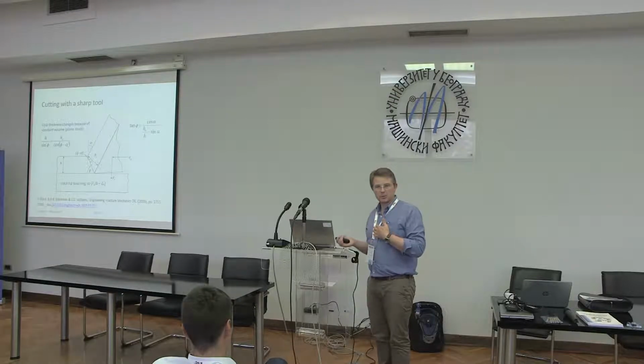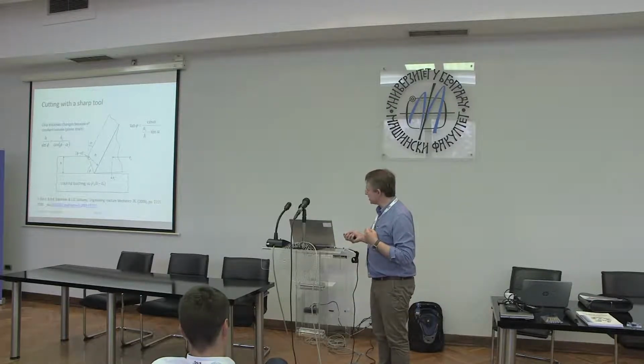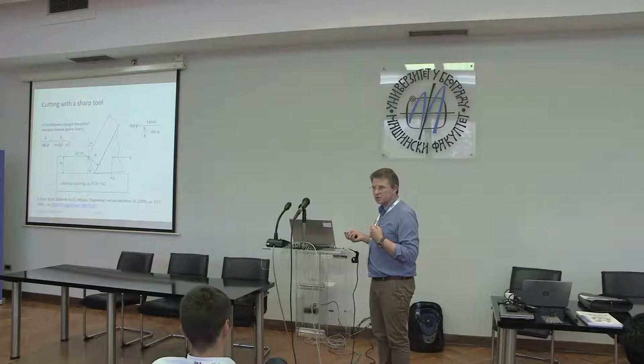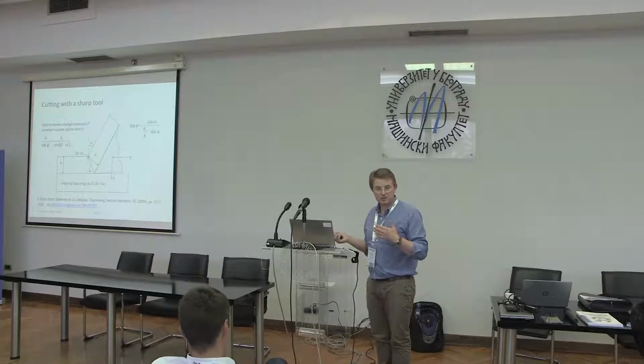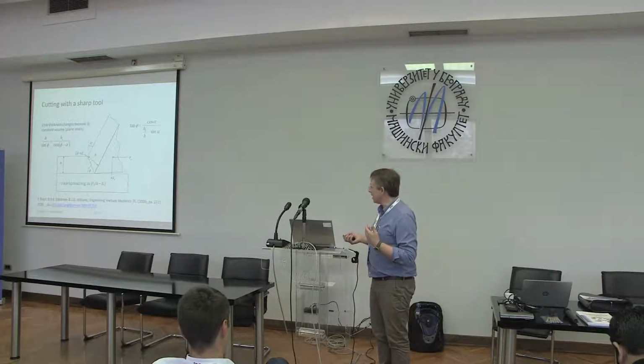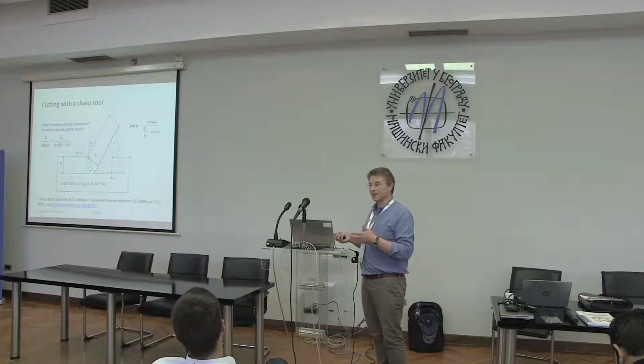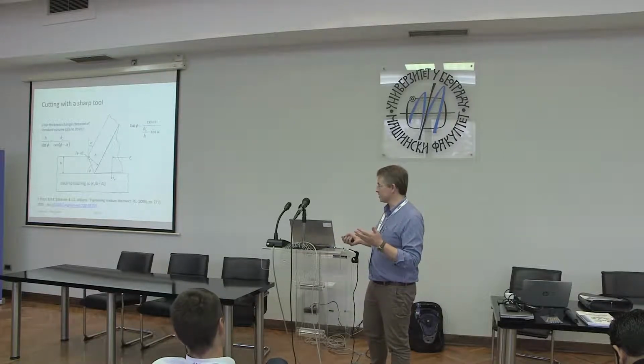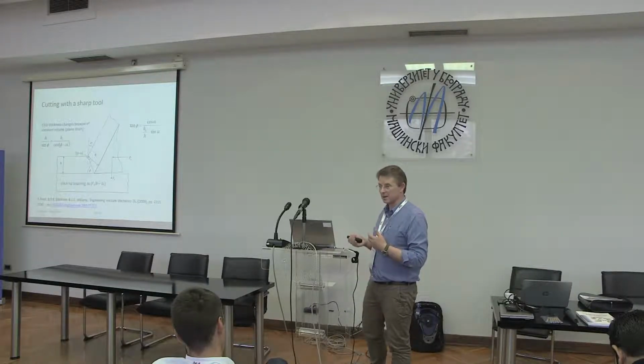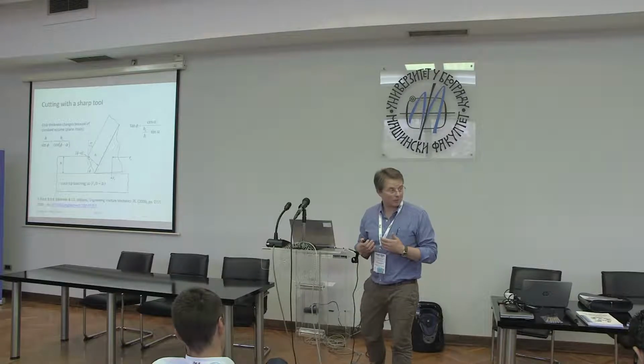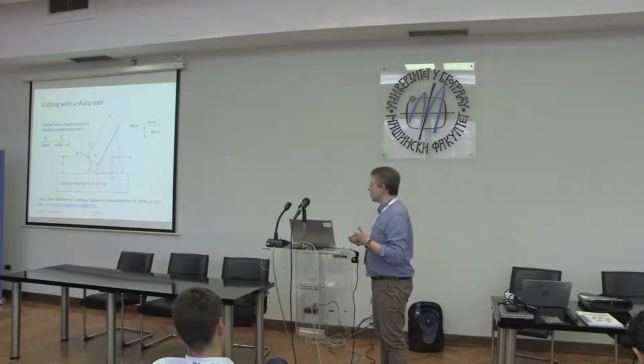And of course the basic idea really is that the plasticity in this point here is a function of the thickness. And in principle, if you can reduce the thickness to 0, you have no plasticity, but you generate the new fracture surface. Okay? So if you develop curves where you're plotting your energy against thickness, you can extrapolate back to 0 thickness and determine a value for energy release rate based upon no plasticity in this point here.